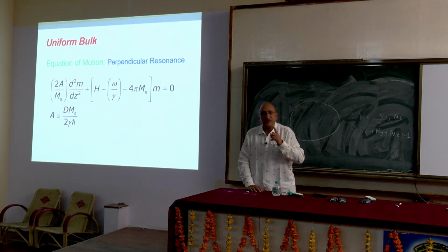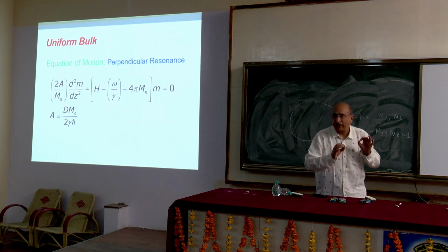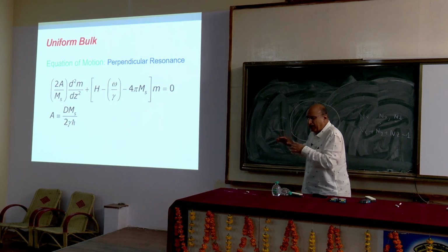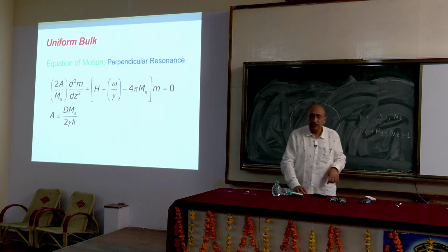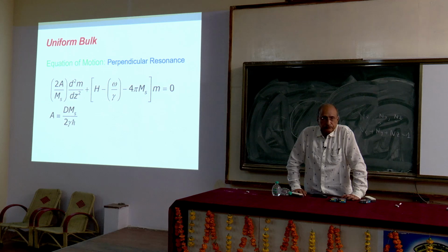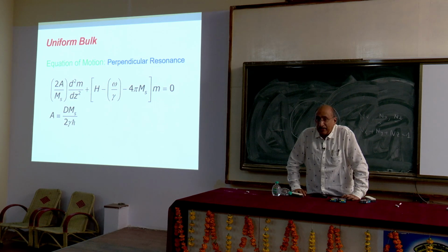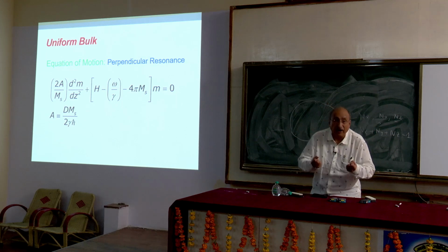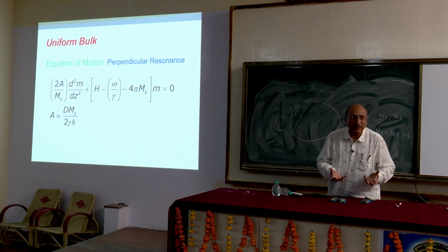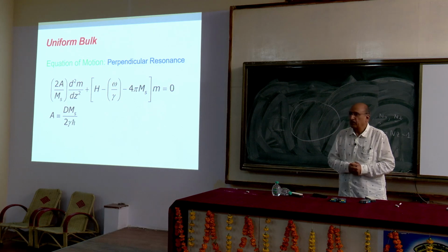So for spin waves, the dispersion relationship at low values of k is of the form ω = Dk². I'm not sure whether it is ħω, whether energy comes here or just omega, but it is of the form Dk². It tells us that if D is larger, the exchange is stronger. If D is smaller, then exchange is comparatively weaker. Okay, is it all right?